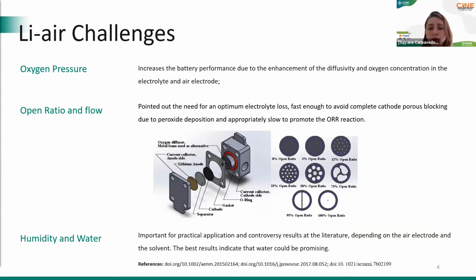Another approach is to study and evaluate the possibility to make holes over the cathode and analyze the open ratio. And the flow over the cathode is another object of study, and it's reported in the literature an option of electrolyte loss due to this flow: fast enough to avoid complete cathode porous blocking due to the peroxide deposition, and appropriately slow to promote the oxygen reduction reaction.